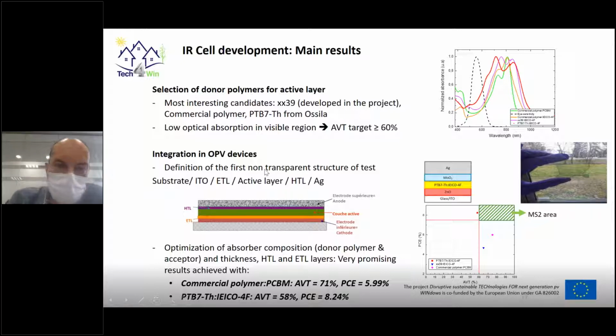So we integrated them in first non-transparent test structure devices, which are represented here. This is a schematic representation in the transparency. This is, in fact, the first. It is still not transparent because we are putting a top electrode, which is a silver electrode on the top. In all cases, we have been optimizing the architecture, the hole transport layer and the electron transport layer. Also, there has been a strong activity in the optimization of the composition of the active layer, which means identifying the donor, the acceptor that is combined with the donor polymer, and the ratio between the donor and the acceptor,